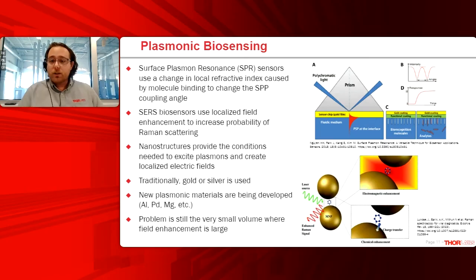So this is a really interesting way to use plasmonics again, but we're talking about SERS today. So with SERS, like I mentioned previously, you generally have these nanoparticles, and your molecule will hopefully fall within that strong electric field region to get a higher increase in your Raman signal. And there are some very clever ways that people have developed to engineer these nanostructures to get extremely high field strengths over the past decades again. However, there's still a problem where you have to ensure that your molecule falls within that very small region, or you have to hope it does.